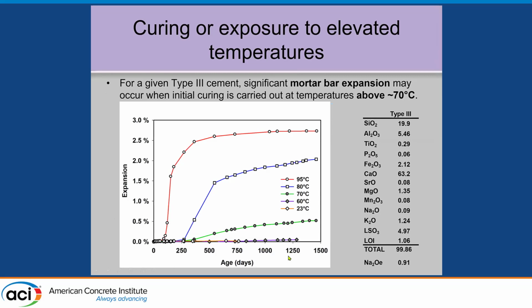At room temperature and at up to 60 degrees C, you don't see any expansion. They just keep going out there without any expanding. The concrete's quite fine. But then when you get to 70 degrees C, in this case, the expansion starts to creep up over time. After about a year, it starts to creep up. And 0.5% expansion is a lot of expansion. We typically talk about 0.04. Expansion is the expansion you need to crack concrete.